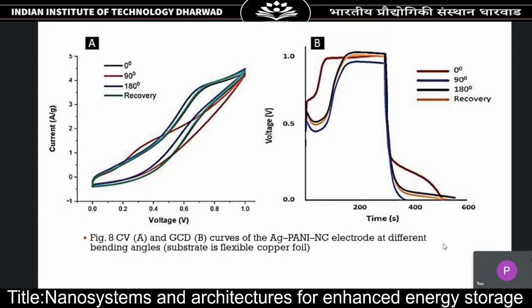An interesting thing was this was coated on copper foil. As we know, copper foil is very flexible. The idea was to make a flexible device, and then bend it through various degrees. We bent the device through 90 degrees and 180 degrees, then allowed some time for the device to recover, and then did the cyclic voltammetry as well as the charge discharge. You can see that there is a considerable amount of recovery, right? If you bend to 90 degrees and 180 degrees, there is some reduction in the area under the curve. But upon recovery, it almost goes to the original area. The same thing is true for the charge discharge. So the idea was to create flexible energy storage devices.